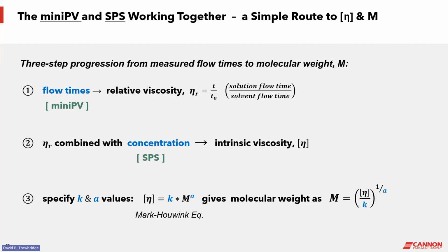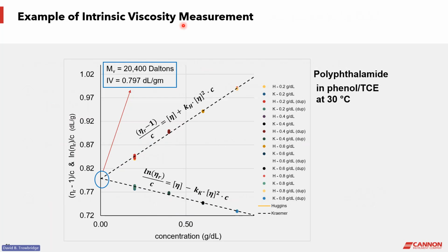Now here's some data on the next slide that shows an actual experiment using intrinsic viscosity measurements on the mini PV. I have here 4 concentrations done in duplicate, and I've extrapolated the Huggins equation and the Kramer equation. They have a common y-intercept, which is the intrinsic viscosity with a value of 0.797 deciliters per gram. And that corresponds to a molecular weight of 20,400 Daltons. This is for polyphthalamide in phenol TCE at 30 degrees C.